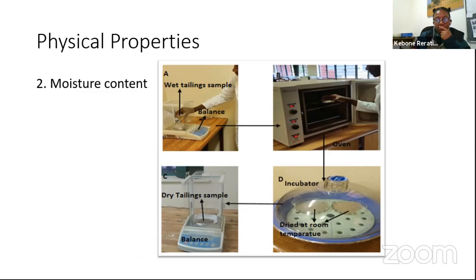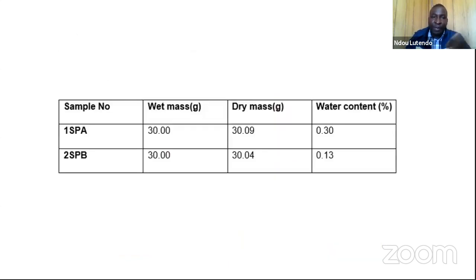I took wet samples, weighed them on a balance scale, then put them in the oven. After that, I weighed the dry sample again from the oven, then dried it at room temperature and then in an incubator, so that no other moisture is lost. And I was able to come up with my moisture content. What I found out is that my moisture was between 0.13 and 0.3%, which is quite a very low moisture content. The wet mass that I got was 30 grams, and the dry mass was 30.09. You subtract both of them, divide, then multiply by 100, and that's when you get the 0.3%.